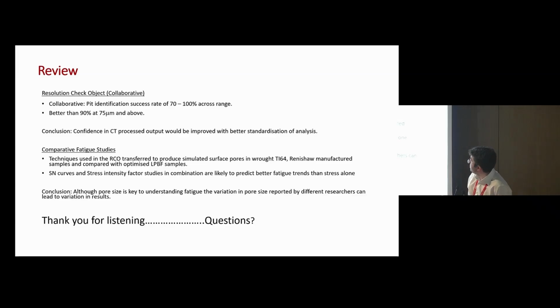So we can produce simulated surface pores, and then look at them, and then I can predict stress. I can get fatigue life better with the SIF rather than stress alone. So pore size is key to understanding the fatigue. Variation in pore size can lead to variation in results.